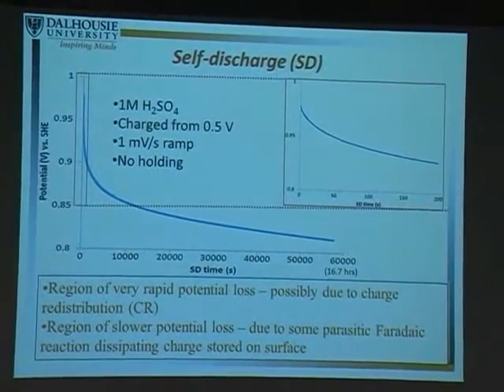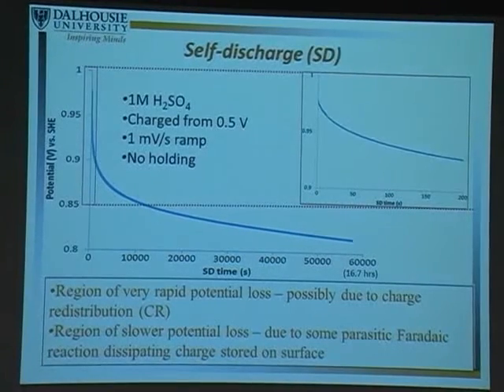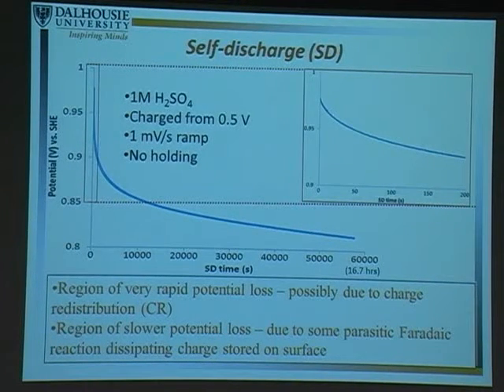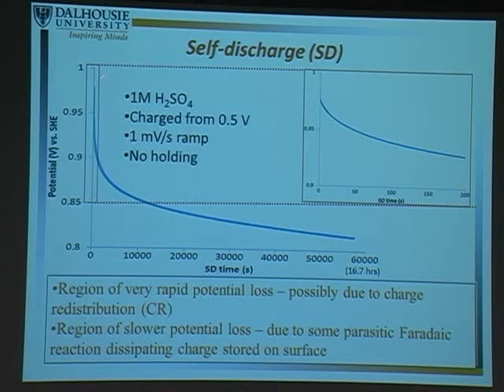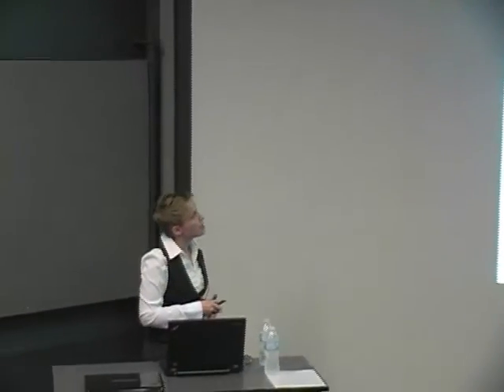And what we want to do is figure out what's happening here. Can we figure out why it's losing charge? If we can figure out why it's losing charge, can we stop it from losing charge and then make the supercapacitors more applicable in more situations? So what we believe is happening are two different processes. One, we thought, was a very rapid charge redistribution. So this is where we put charge on the surface and we open the circuit and that charge moves through the electrode. And I'm going to describe our research into that. We also believe that there is a Faradaic reaction happening on the surface. So the reaction of something in the cell which is stealing charge essentially from the electrode surface. And I'm going to talk about our research into that as well.